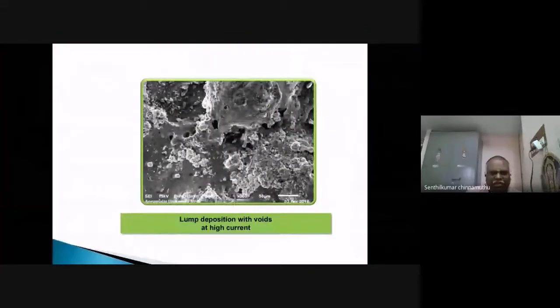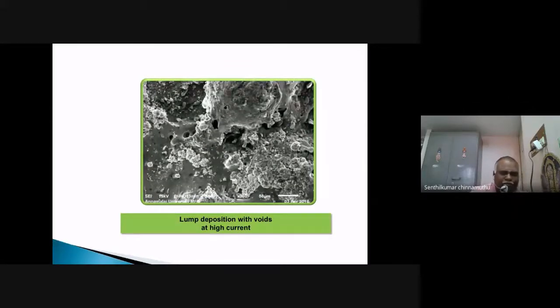At high current, more amount of material is deposited, vaporized and melted, and gas bubbles are formed. The gas bubbles are evacuated from the surface of the workpiece, so that voids are formed. The gas bubbles generate the voids, and the higher current determines the void size. Higher the current, more the voids, and the size of the voids is also higher.